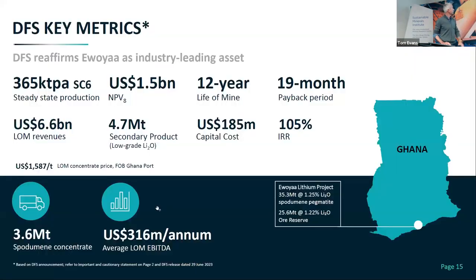So all of that delivered these DFS metrics. We won't go into the details, but it's a 2.7 million tonne per annum run of mine operation that runs for 12 years with an NPV of over $1.5 billion, capital costs of 185 million and payback within 19 months. So that is really significant. And when you compare that to, say, a gold mine, you're looking at equivalent grades of 8 to 10 grams per tonne gold from a value point of view.